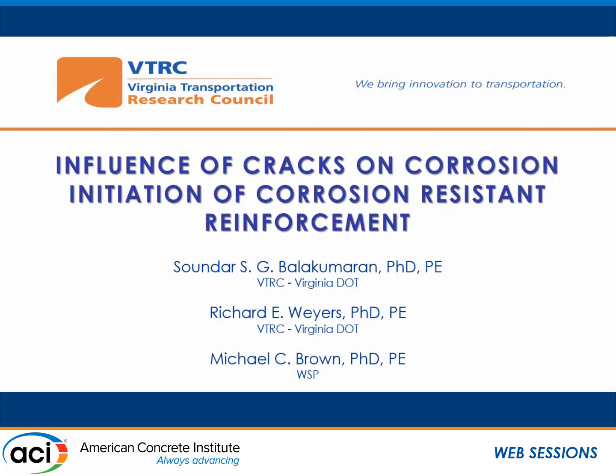But we realized that the idea behind these crack control strategies is that cracks would allow an increased amount of chloride diffusion to happen and thus lead to significantly increased corrosion at some point. So VDOT has also adopted corrosion-resistant reinforcement in concrete decks in the last decade. So we wanted to see the effectiveness of both these mechanisms. We want to see how the cracks affected the corrosion initiation in the corrosion-resistant reinforcement.